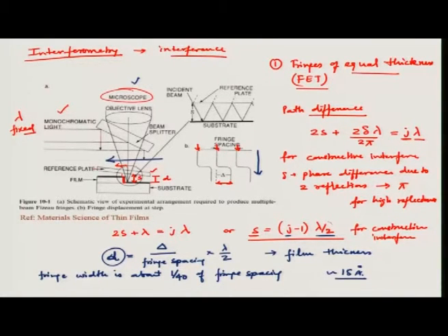So, this is the detection limit, but you have to make a step onto yours by scratching or by some other method, so that there is a step between film and substrate. Also, you should coat it with high reflective material, and it should be very thin so that it does not add to your film thickness. So, this is one method.